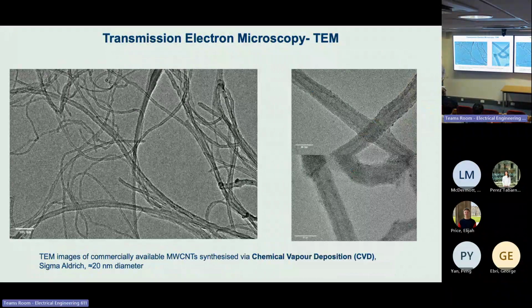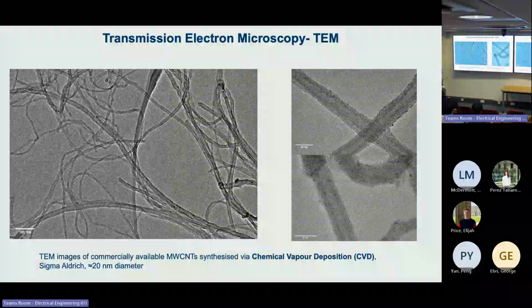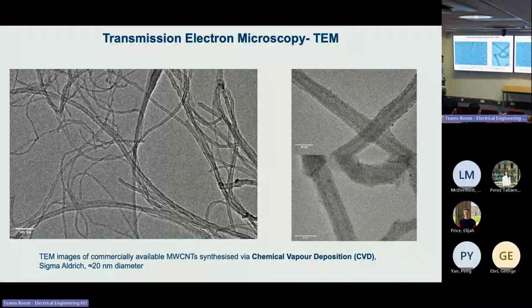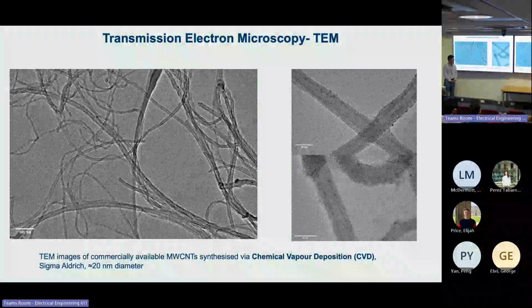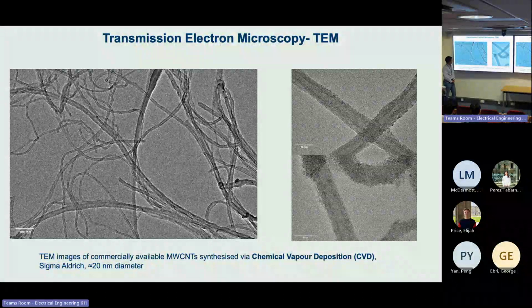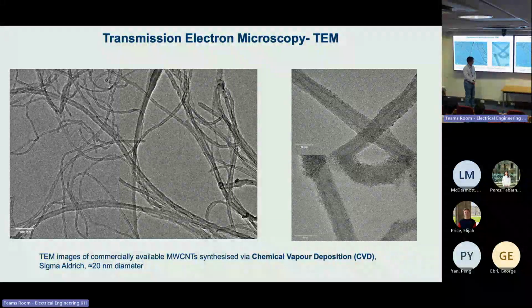We also did some TEM on our products and also on the commercially available CVD carbon nanotubes. So these are the TEM images of the CVD synthesized carbon nanotubes. You can see its hollow structure in the center. SEM can only see the outside of the carbon nanotube, but TEM can see whether it has a hollow structure, so whether it's a carbon nanotube or a carbon nanofiber.